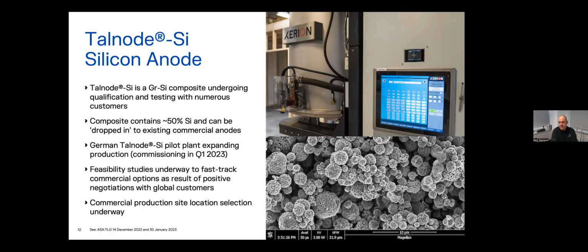Why we would take on the ambition of an added project instead of just what we're doing in Sweden is because we've had very positive outcomes of negotiations with customers that have been testing the material, and there are targets for commercializing this material. So we're looking at sites where we want to build a refinery to start producing commercial quantities of Talnode Si. The beauty of this is it actually is byproducts of our Swedish anode making for Talnode C, and you can take those byproducts down to Germany, smash them up, and build this much more complex silicon particle, which has a much higher price point, but has a certain demand in the market.